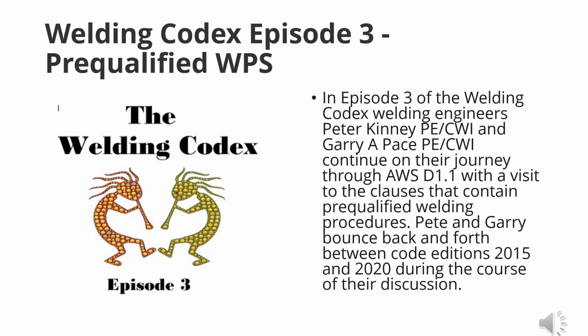And I say this because, like Pete and I were talking, if you're welding some of these weird materials in power plants, you've got to do the hydrogen bakeouts and whatnot. These are not those materials. These are hit it with a little bit of preheat, weld it together with some low hydrogen material or one of the pre-approved welding materials, and you're not going to have too many issues. Correct. 90% of the population should be able to get this.